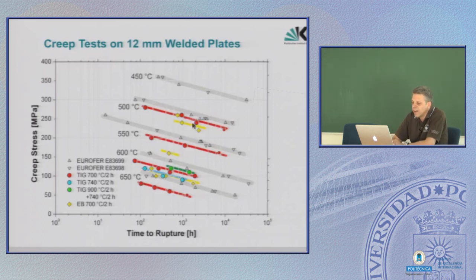And you see in all cases the colored curves are below the gray ones, and gray ones, this is base material, and the colored ones are the joint materials. So whatever you do after welding, the creep properties are worse compared to the baseline materials. In the best possible case of a post-weld heat treatment, you can see here these are the green dots, and green again means a full heat treatment, which is always useful for Eurofer welds, but again cannot be used for these breather boxes.